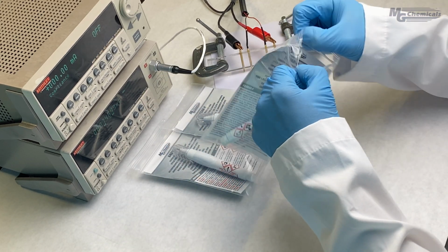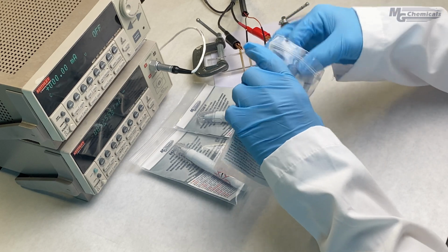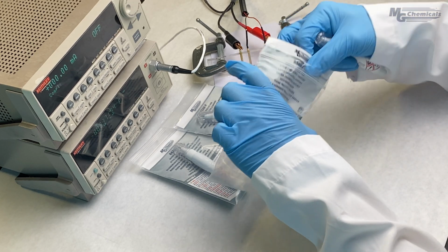Here, we're using our conductive acrylic pens, but this works for other formats as well, such as liquid or aerosol formats. First, we prime the pen to get the conductive ink flowing before we apply. Then, we apply the ink in a smooth, even motion down the entire length of our line. Had we sprayed the coating, we would have got a thin, even coat.